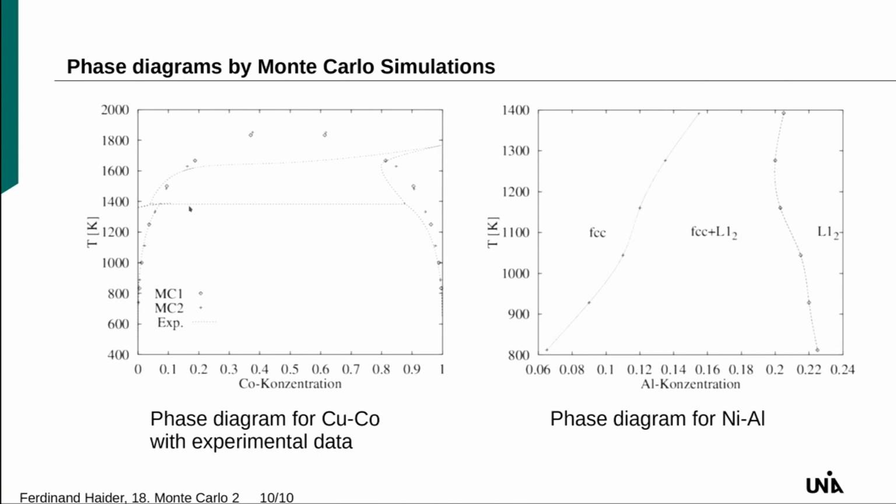And that's the experimental phase diagram, the dotted lines. So in this case, it more or less at least reproduces this side of the solubility line. This one is not that well matched, but still reasonable, I would say. I used 2 different sets of parameters here, I forgot which one, to fit these pair exchange energies to this phase diagram.